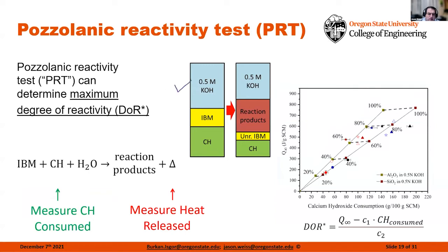So what is the pozzolanic reactivity test? We're going to take a little bit of alkaline pore solution. So this is going to look like a pore solution and get us up to a pH of about 13.4. We're going to take our SCM, or our industrial byproduct, and use that, and we're going to react it together with calcium hydroxide. And when we do that, we're going to actually produce heat, and we're going to consume some of this calcium hydroxide.